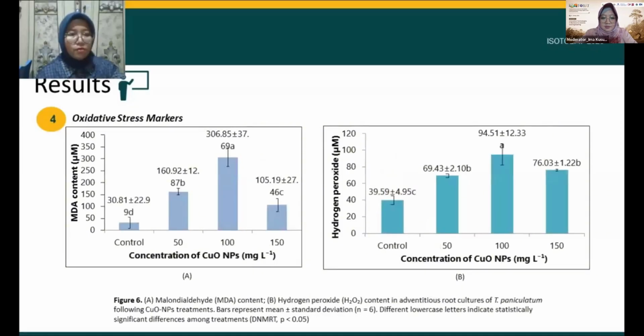4. For oxidative stress markers, malondialdehyde and hydrogen peroxide content were significantly influenced by copper oxide nanoparticle treatment. MDA content increased substantially at moderate copper oxide nanoparticle concentration, with the highest level at 100 mg per liter. A comparable trend was observed for hydrogen peroxide accumulation. Copper oxide nanoparticle treatment induced a concentration-dependent increase in hydrogen peroxide levels, peaking at 100 mg per liter. This result indicates enhanced oxidative activity in response to copper oxide nanoparticle exposure.